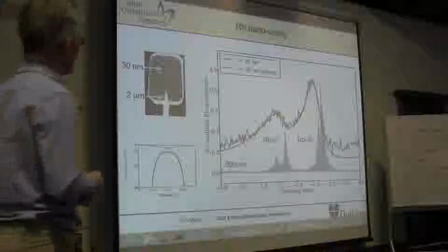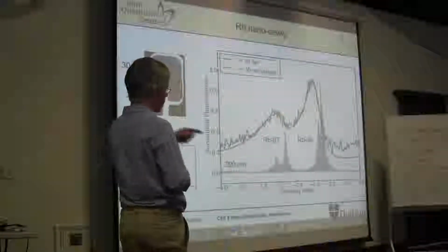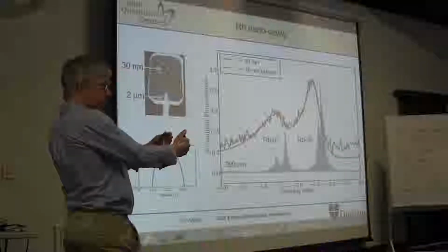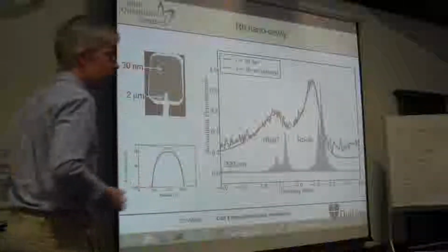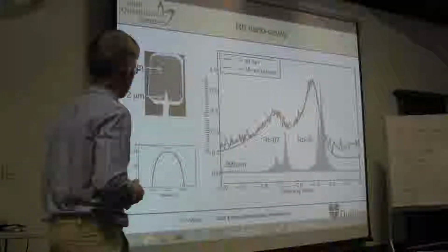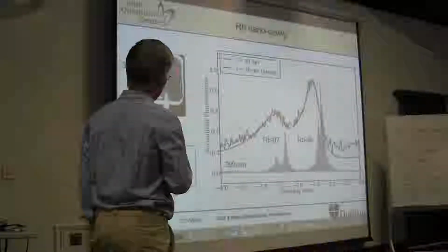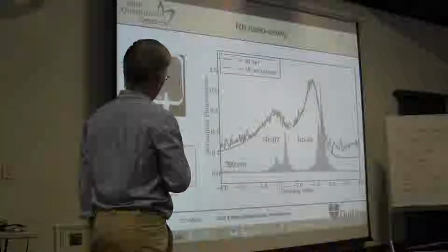Interferometric. People always ask, how do we know it's 30 nanometers? Well, we just reflect a laser beam, and because there's two surfaces, you can calculate the distance interferometrically. So you use laser interferometry and you get the distance, which is nice. So we can measure in this 30 nanometer region, and we measure fluorescence.